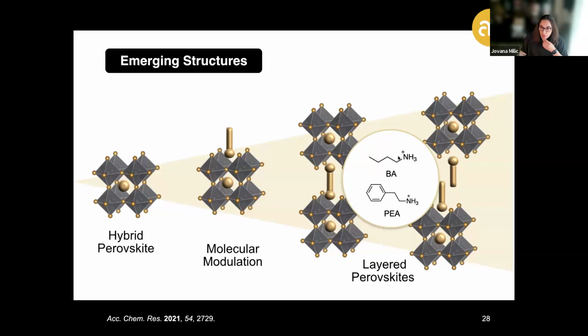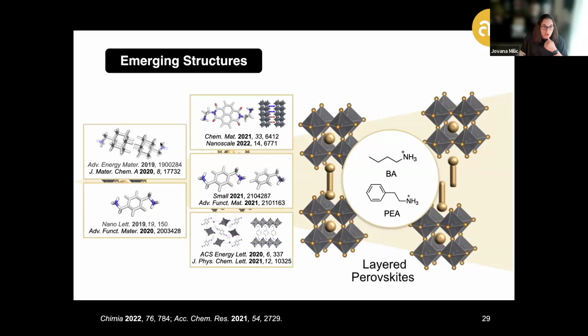For this purpose, we have expanded the scope of these systems by tailoring the underlying interactions, such as the van der Waals interactions based on alkyl chains, strengthening them through introduction of carbocyclic elements in adamantyl-based systems, or functionalizing aromatic systems by shortening alkyl chains from ethyl linkers to shorter methylene ammonium-based systems, introducing functionalities to access the corresponding Dion-Jacobson phases.